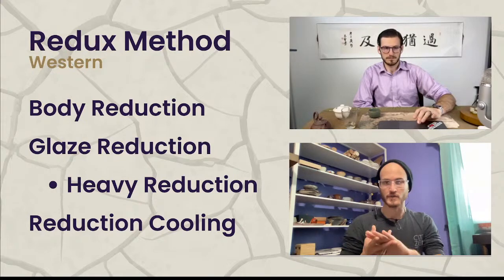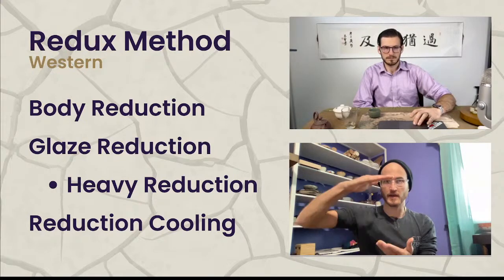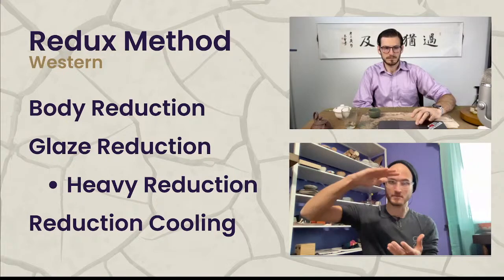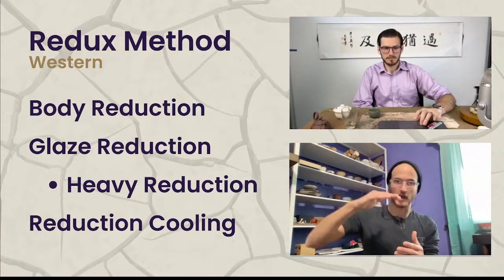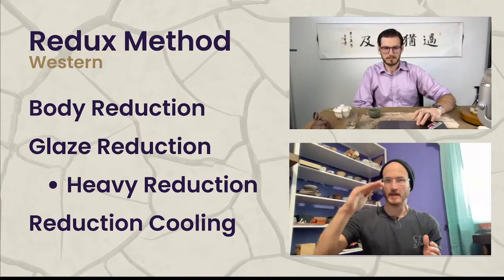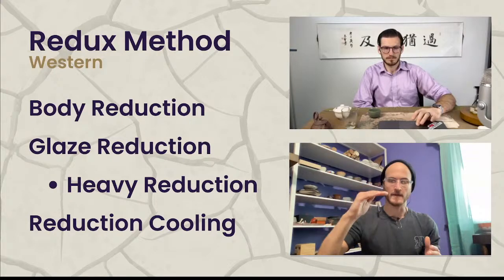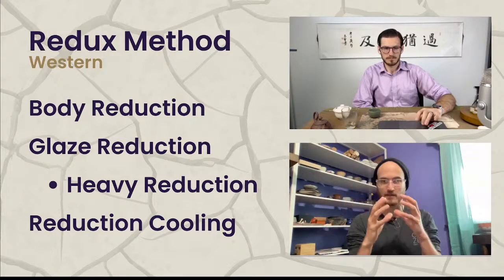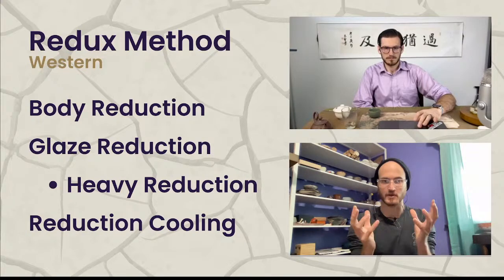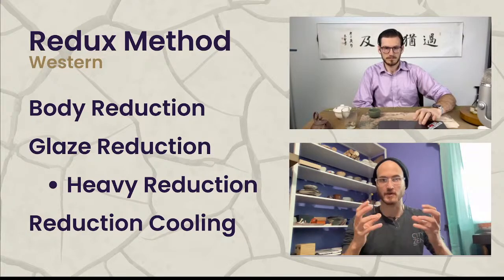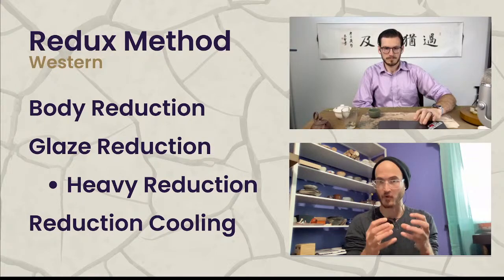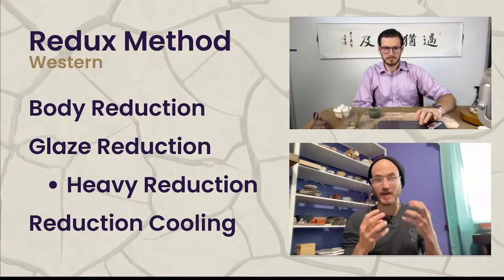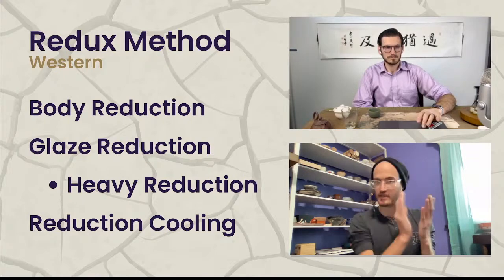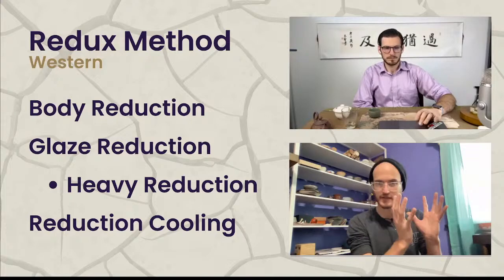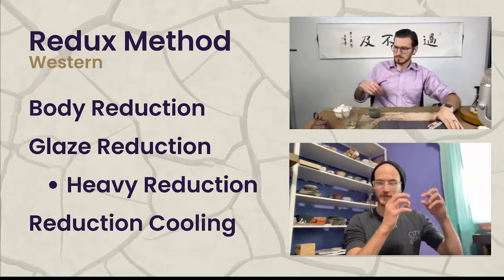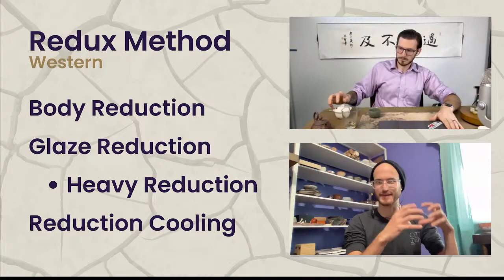So if you get to your peak temperature and then you let it cool naturally, which just means you're cooling it as slowly as possible, you're closing everything up, and it's just sort of dropping naturally, what ends up happening is that the glaze and clay are still interacting with the surface and they're still staying hot. So glazes are more likely to run more. They're more likely to be very shiny because you've sort of just sealed off and you wait for the surface to do its thing slowly. So it slowly cools and becomes very shiny.